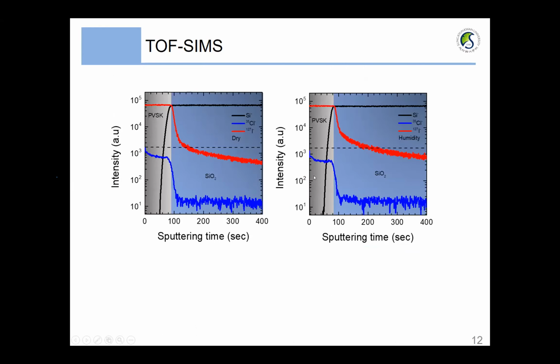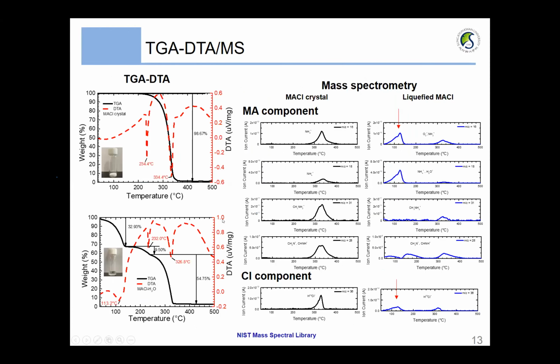For the finalized films, the TOF-SIMS result showed that, compared to the dry sample, the humidity condition shows a lower content of chloride. And then, to determine why the MACl evaporation or elimination is facilitated by the humidity, we continued to check the TGA coupled with DTA analysis.